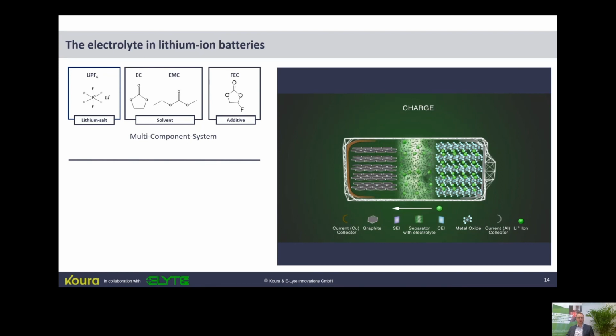So as we humans need the blood to survive, every battery needs the electrolyte to survive. The electrolyte is a multi-component system, so we have a lithium salt, typically LiPF6, dissolved in a mixture of cyclic and linear carbonates. This is a so-called mixed solvent approach, where we try to marry advantages of both substance classes. On the one hand side, the high dielectric solvents, the cyclic carbonates, together with the low viscosity solvents, the linear carbonates, in order to get a very low viscous system. Furthermore, we have some performance additives in order to tailor special properties of our electrolyte, targeting special applications.